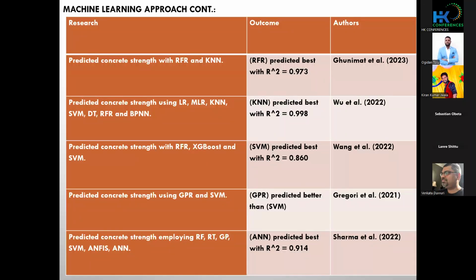So sorry, please. Okay, so starting from predicting compressive strength of concrete with machine learning approach, over the years, several researchers have actually utilized this technology to determine strength of concrete, starting from Ghunimat et al. They performed an experiment where they predicted the compressive concrete strength with random forest regression and k-nearest neighbor. They found that random forest regression predicted best with correlation coefficient of 0.973, and that's high enough.